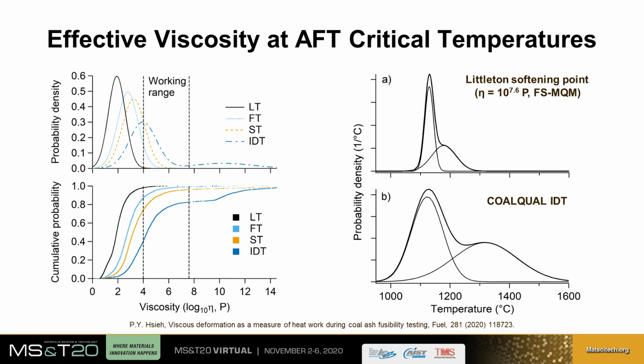A possible answer is that the Littleton softening point temperature of a coal ash mixture is just below its liquidus temperature, as suggested by prior work on pyrometric cones. There is some evidence of this when one considers the predicted effective viscosity of coal ash slags at their AFT critical temperatures. The effective viscosity of most coal ash cones lies within or below the working range of glass once initial deformation begins. Therefore, much as was the case for pyrometric cones, the deformation of coal ash cones during fusibility testing is the accumulation of viscoplastic deformation due to gravity and surface tension over time.